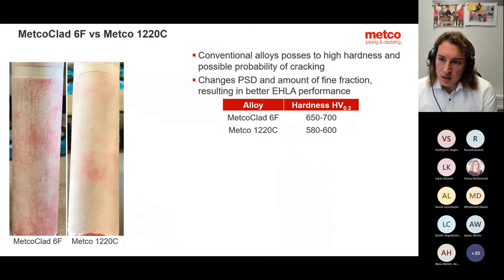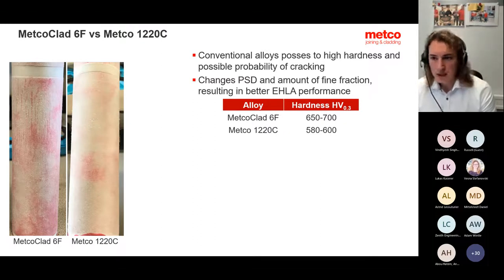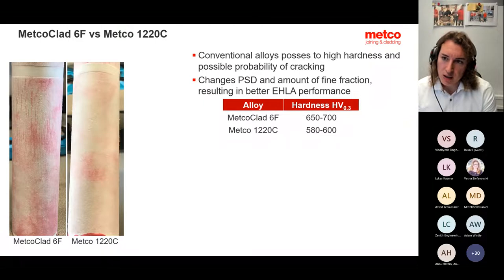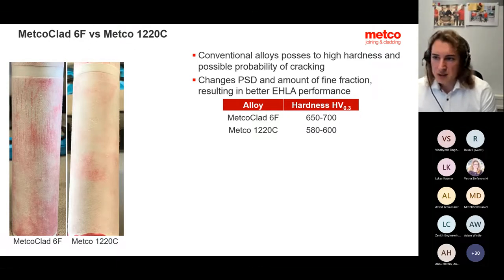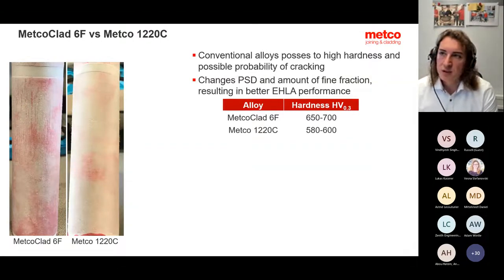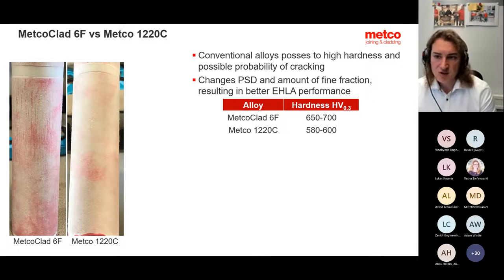This is true not only for, let's say, new materials development. This is also, to a certain extent, we have found out, works for commodity materials. Best example, if we talk about high-speed laser deposition of Stellite 6, first, we were very surprised when we found out that our powder MetcoClad 6F, which was our classical Stellite 6 material with a lower powder cut suitable for high-speed laser cladding, got us in trouble in terms of crack formation already at the first layer of deposition.